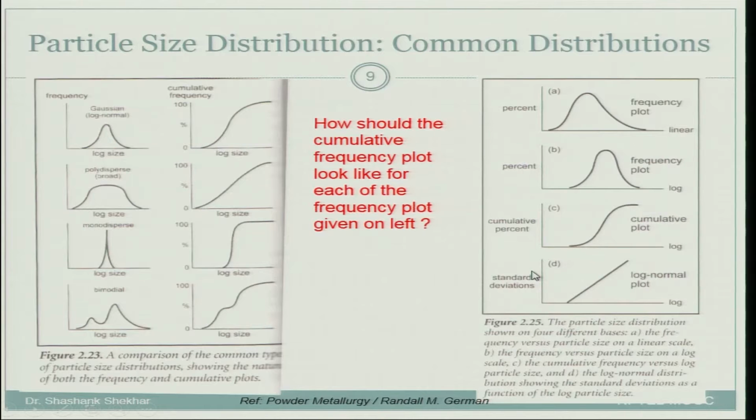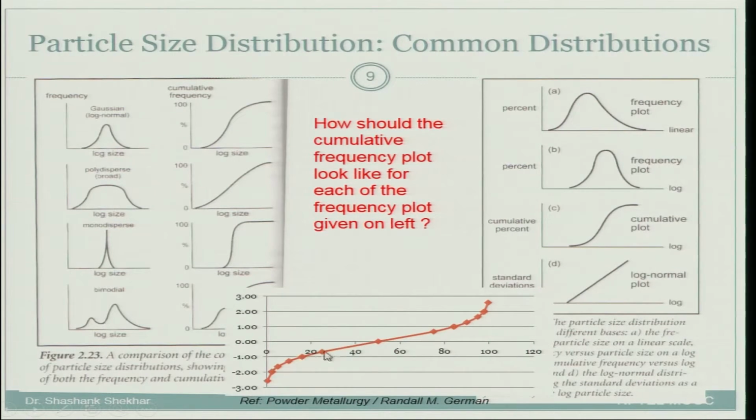Now, this is a very useful plot, because whenever you have a normal distribution, or in this particular case a log normal distribution, you will always get a plot like this. So, what is it representing? Fraction of data, or equivalent to that, what is the equivalent diameter. So, for 100% data you will get a D100, for 50% data you get D50, where you have the mean value, and for 20% data you get D20. And just to bring back in our memory, we are talking about log diameter. So, this is not really D20, but log D20, this is log D40, log D60, and so on.